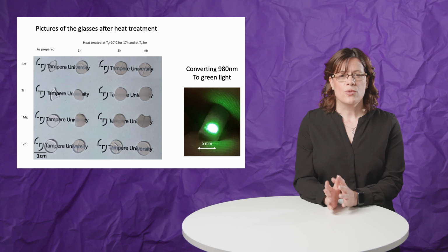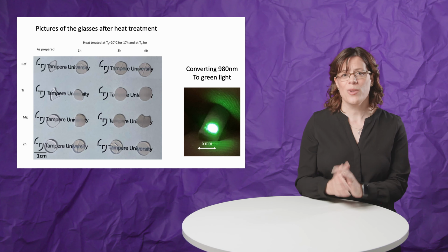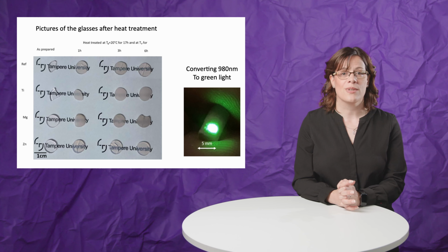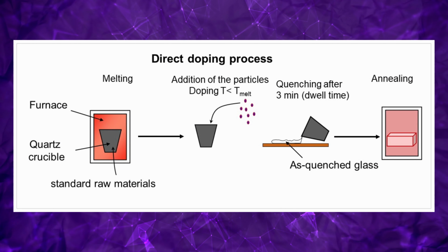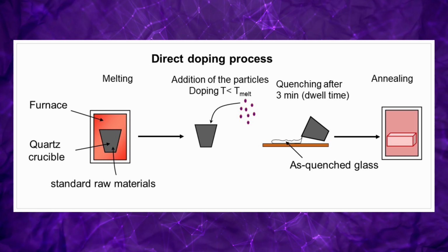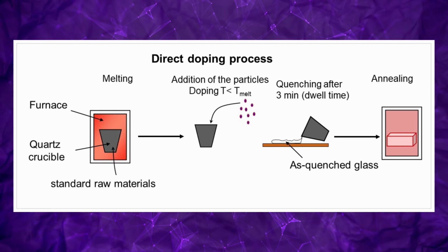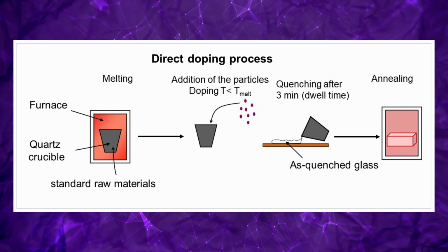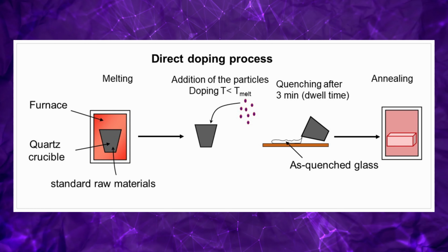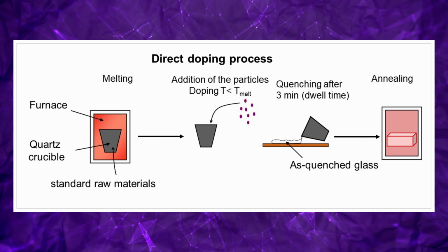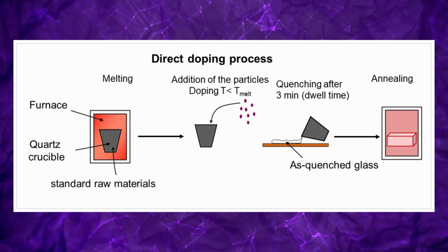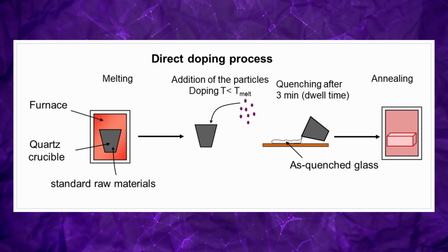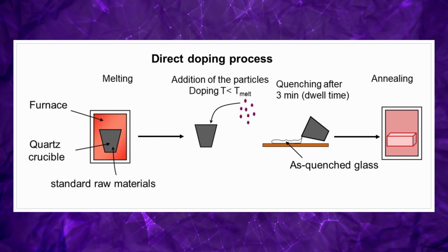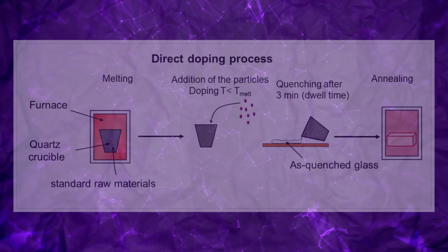As it's not possible to control the nucleation and growth mechanism in glass, we have worked on the development of composite materials. These composites are composed of a glass matrix and crystal. So first, the crystal with specific phase and dopant levels are prepared, then added in the glass melt before quenching. In this process, it's crucial to identify a suitable temperature for doping and dispersing the crystal in the glass melt to succeed in doping the glasses homogeneously with particles. The particles need to be, of course, thermally stable at this doping temperature to ensure the survival of the particles within the glass during the glass preparation.